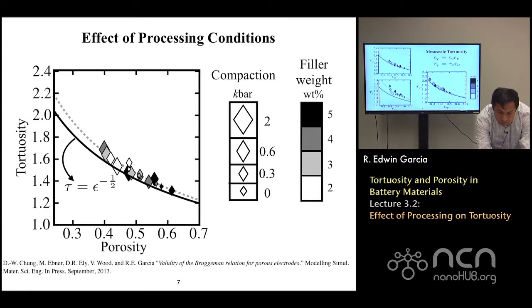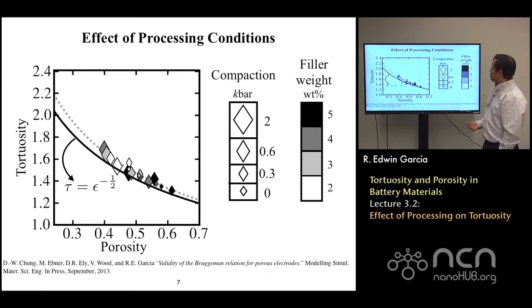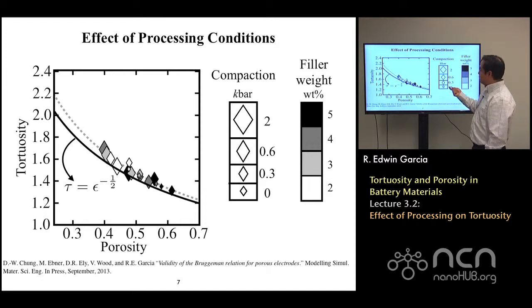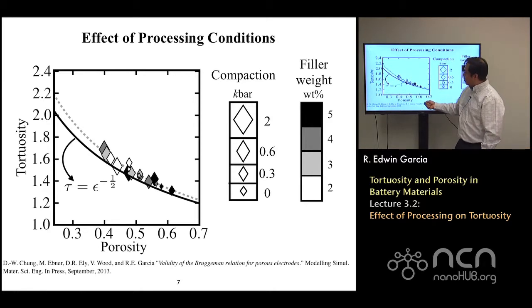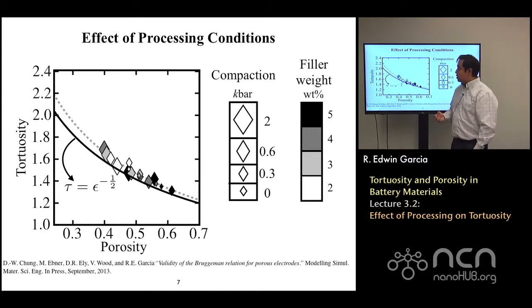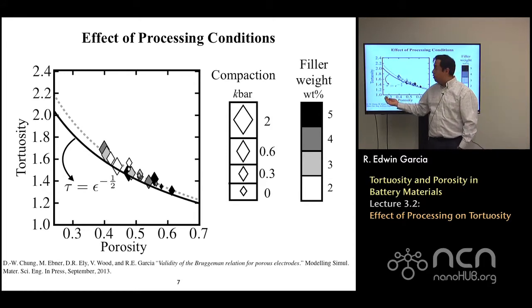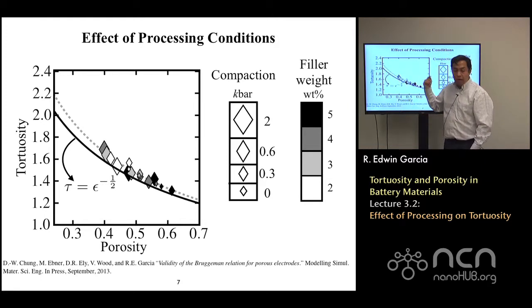Here is just to show you once more the effect of the different contributions. When this data is replotted in the correct space, we can recover the effect of tortuosity as a function of porosity, and we are very close to the 1 over epsilon to the one half response, but consistently above the line. For those interested in getting the tortuosity effect just right, it is very interesting to see how there are some deviations with respect to that ideal. Especially since at very low porosity, those deviations can be greatly amplified, and we will have to truly account for them.